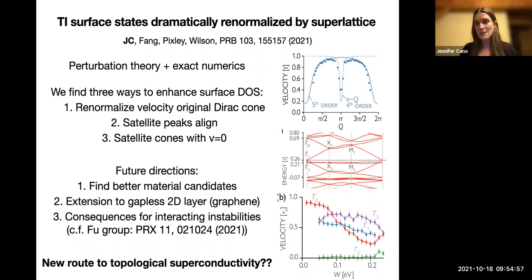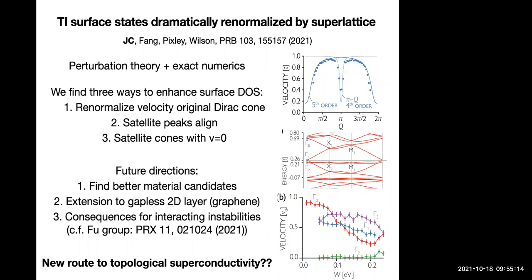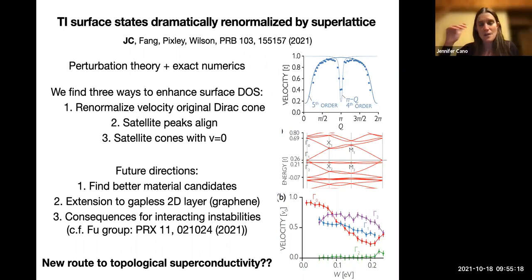Now, there's a different aspect to this, which is that the magnetic TI obviously breaks time reversal. And so then you could actually realize a gapped miniband. Here we're always keeping time reversal because we're not studying any interactions. But I think in the magnetic TI, you could see something different, which is that you could open a gap to that flat band. And I think that would be pretty desirable because then you could create a gapped flat band, which is even more analogous to twisted bilayer graphene.